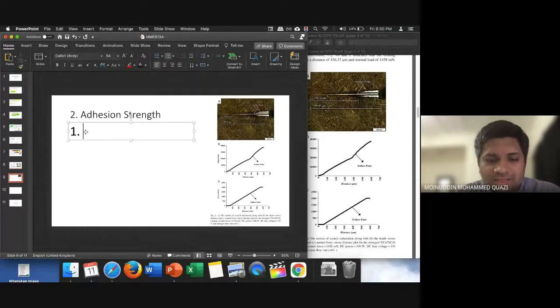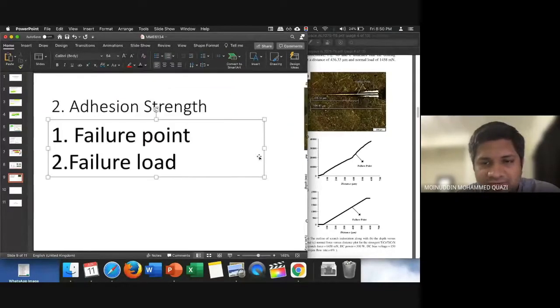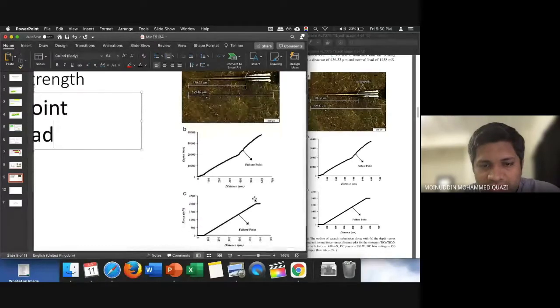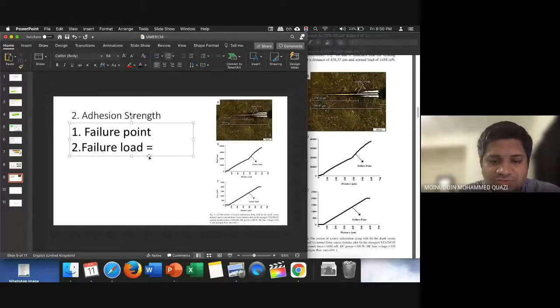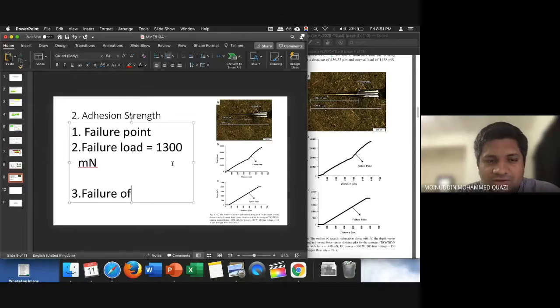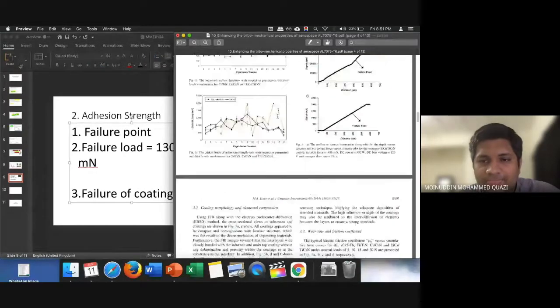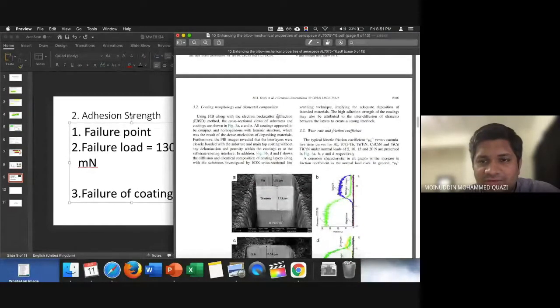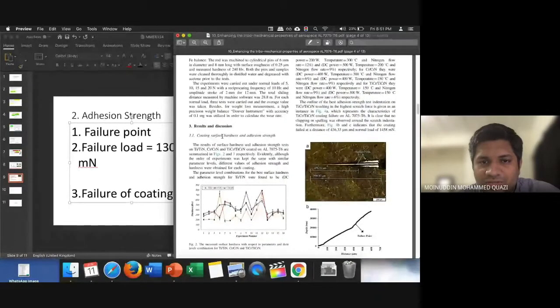Okay, number one, failure point. Number two, failure load. As you can see in the figure, the failure load is about 1300. Okay, it should be mentioned also. So failure load was equal to 1300 millinewton. Then you're going to show failure of coating, adhesion failure of the coating. So go and read the article, okay, and you will find the failure of the coating. Okay, coating hardness and adhesion strength.